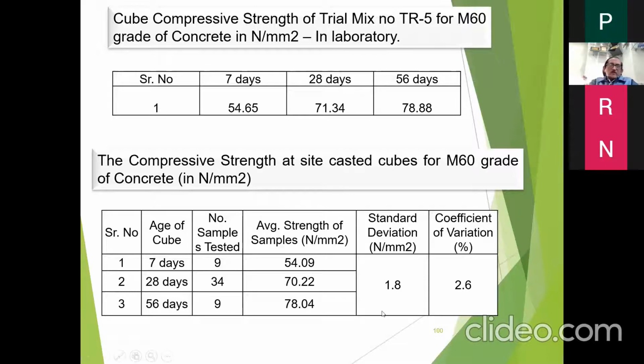And these were the laboratory strengths. 54.65 was the laboratory strength at 7 days. Against that we got 54.09, a good conformance, then 71.34, 70.22, and 78.88; we got 78.04 average compressive strength. The standard deviation was 1.8 newtons per mm square, and the coefficient of variation was only 2.6,